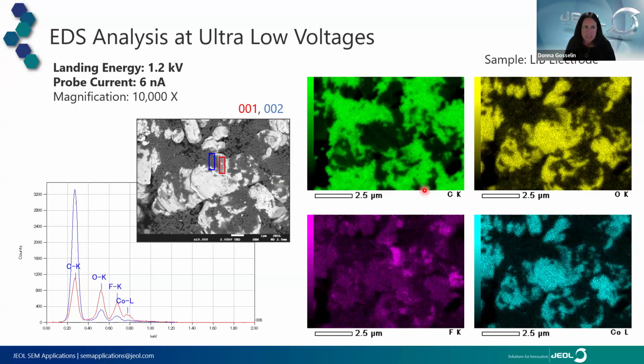One of the benefits, again, of doing this low voltage analysis is that our penetration depth is very small. So the mapping is going to be more representative of the composition that is on the surface, and that's readily apparent here. We can differentiate the fluorine-rich and carbon-rich areas. The lighter elements will also be detected more accurately since the X-rays have less chance to be absorbed within the material. And this low voltage analysis also allows for better analytical spatial resolution.